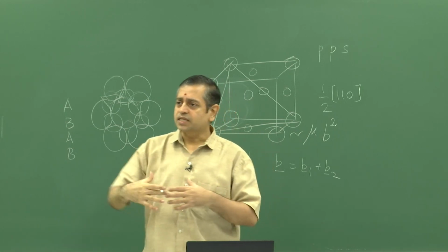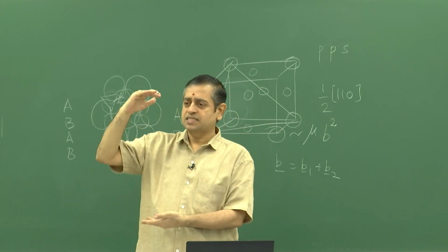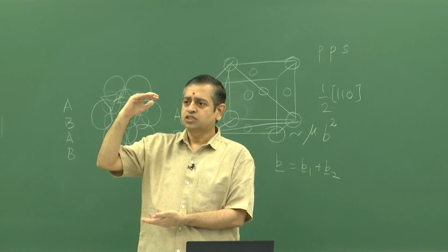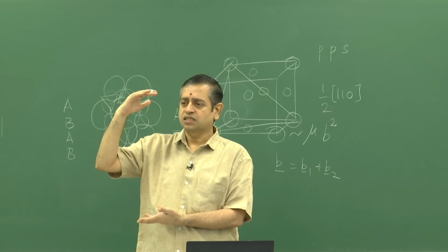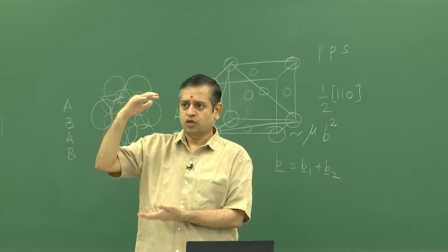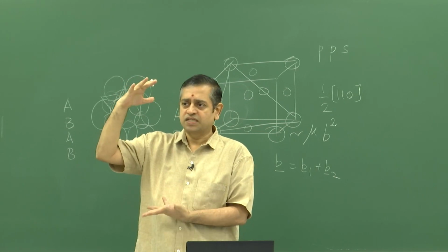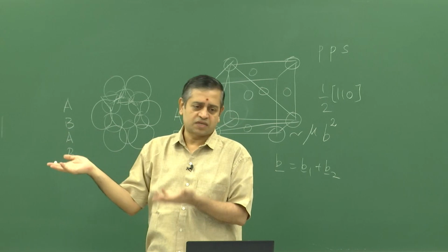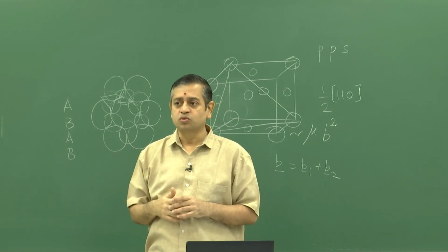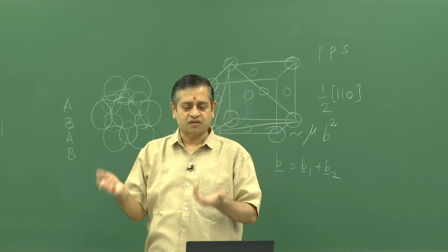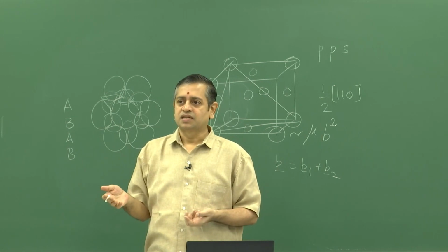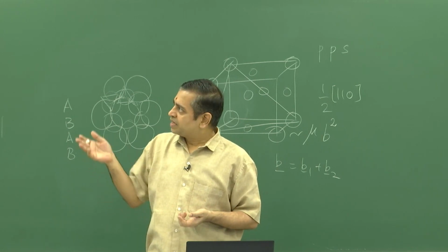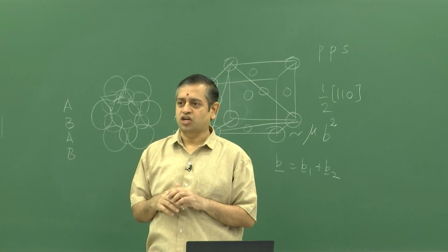So, it is periodic in the x and y directions, and in the z direction it is not periodic. It is a shrink wrap. No atom can escape, but it is a free surface. But because we also wanted to use this system to do the thermodynamic integration and calculate the stacking fault energy and so on, we did not want this free surface on top.